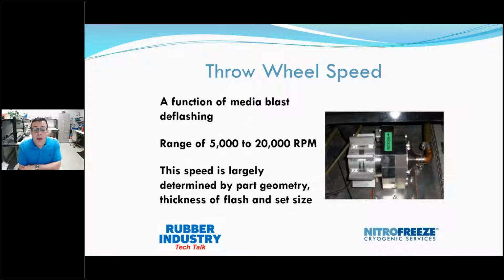That speed is going to be determined by part geometry, thickness of the flash, and your batch size. In a lot of older equipment, I've seen that the throw wheels will only go up to, say, 10,000 RPM. One of the issues with that is that it takes longer to deflash. Ideally, at the end of the day, we want to do this efficiently and ultimately to make money. So with speed, we find there's a sweet spot.